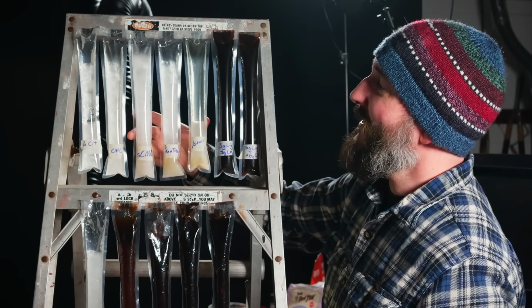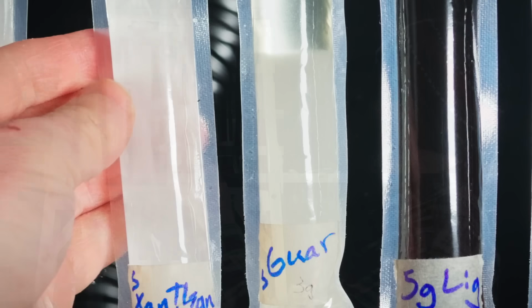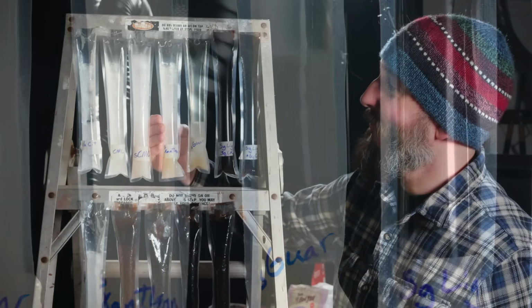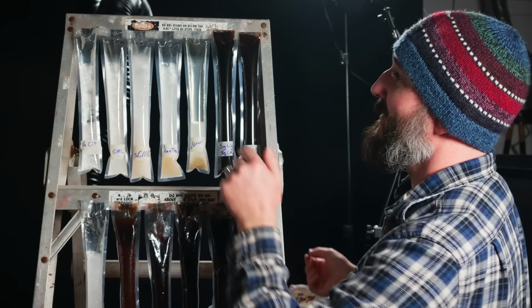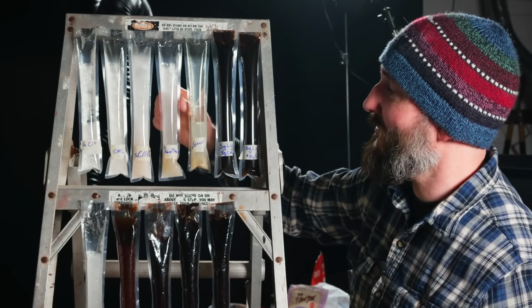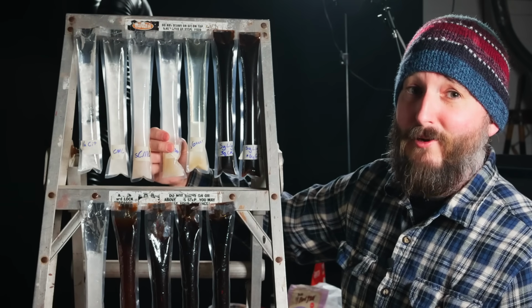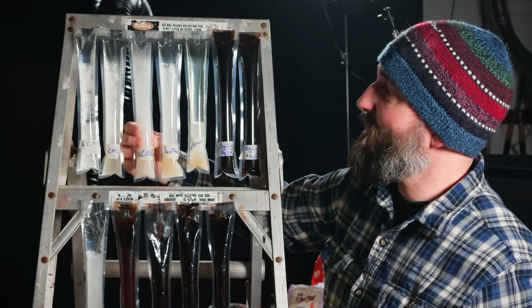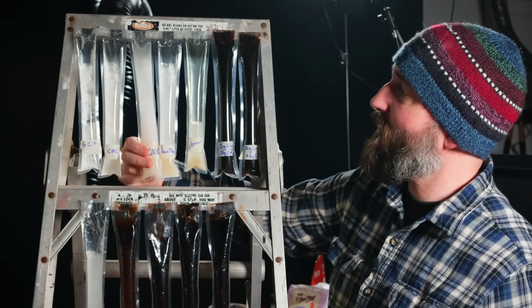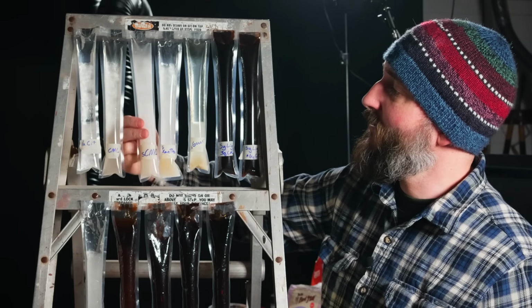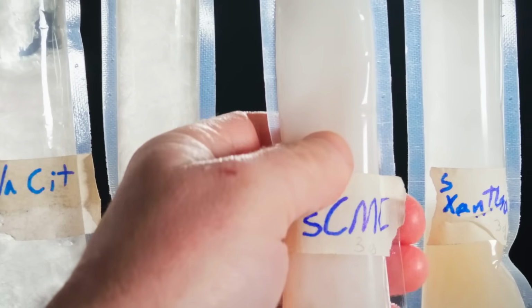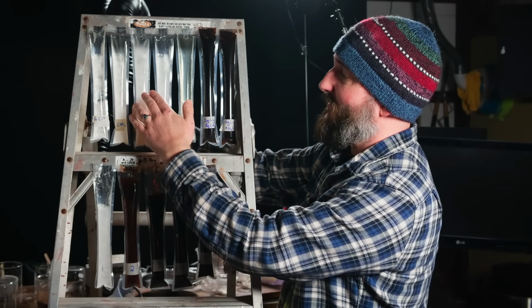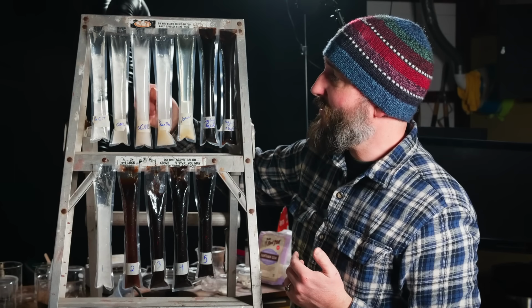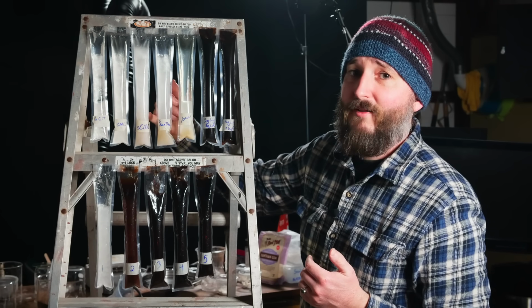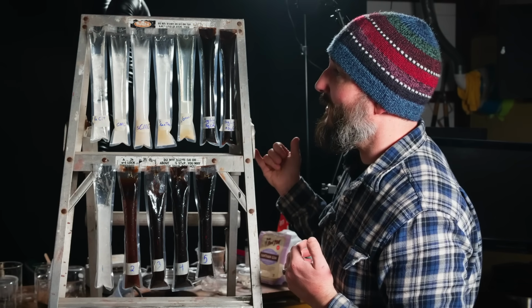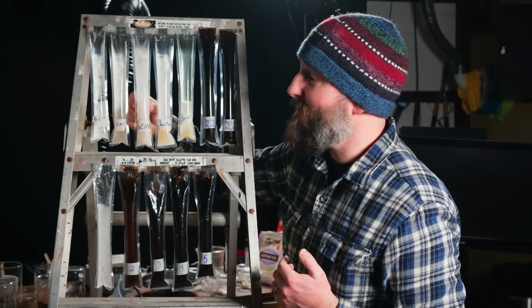So these 3, the xanthan gum was the one that performed the best. This, in fact, was really well homogenized while frozen, and it probably still is, despite this top section now being in a molten state. The xanthan gum performed really well. The sulfonated CMC was a little slower to freeze, but it too is very soft, no hard crystals. However, before this one actually fully froze, something settled to the bottom of this. And so again, when this remelts, whatever is already at the bottom is going to stay more concentrated in that area unless we agitate it.